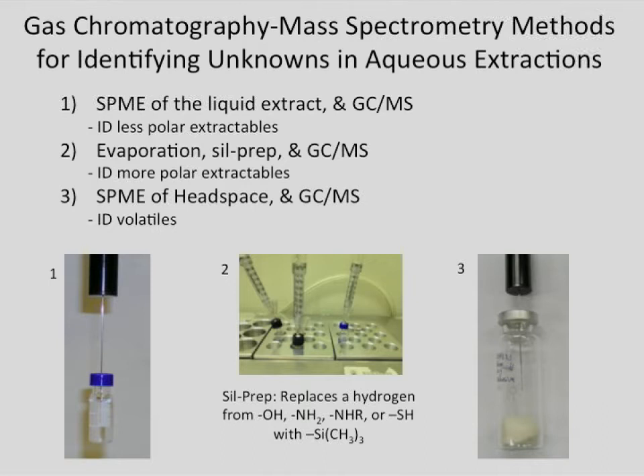This is the second method: evaporation and then functionalization with a trimethylsilylating agent. And so what that does is we allow these samples to dry. The ideal is not to heat them.